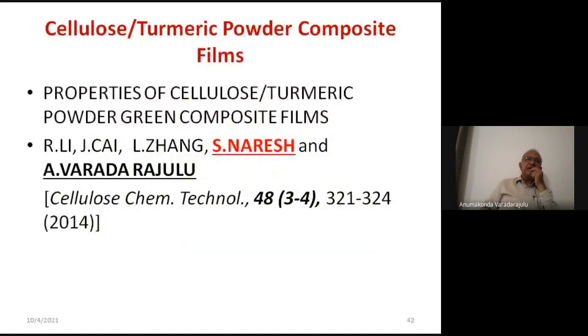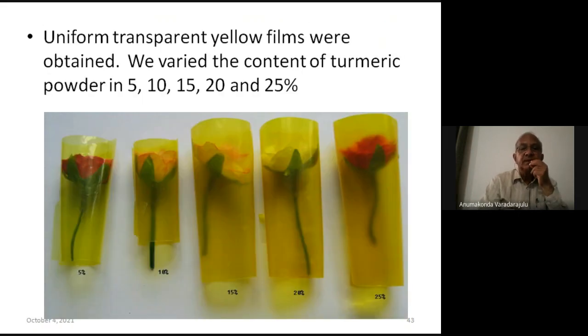Then for medical applications, we used turmeric powder as the filler, and we made the cellulose turmeric powder composite film. This can be used for both packaging and medical purposes. So these are the films. We loaded up to 25% of this turmeric powder. You can see the deepening of the color with concentration. So these are the rose flowers wrapped with these films.